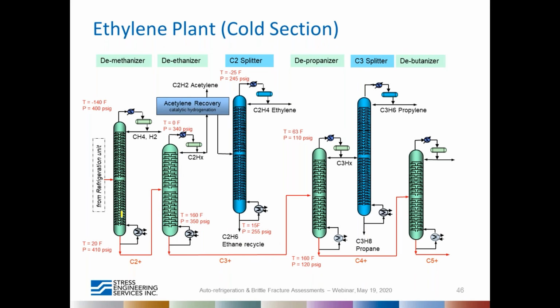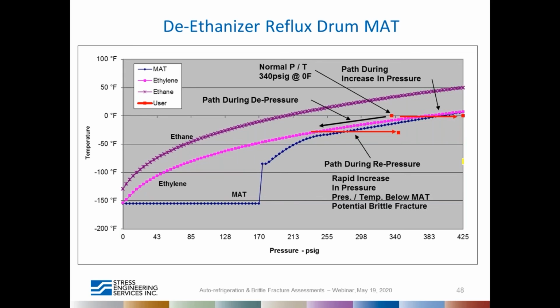Now let's look at one particular vessel. In some of the vessels, there may be different materials of construction from the bottom to the top, so you may need to develop different MAT curves for each section. Let's look at one particular example here. This is a drum that's operating at a pressure of 340 psig and a temperature of 0 F. Let's look at the MAT curve for this vessel. In this case, it's the deethanizer reflux drum. There are two CET curves provided. One is for ethane and the other one is for ethylene, ethylene having the lowest operating temperature, or the lowest CET. It is no coincidence, right? So you can see that the MAT from API 579 based assessment can only go to -155. And if you look at the ethylene's lowest CET, it is -152.